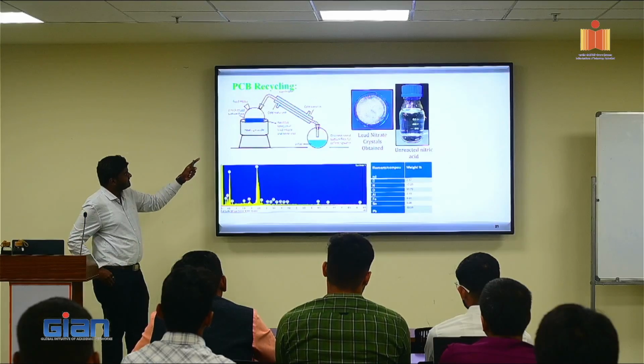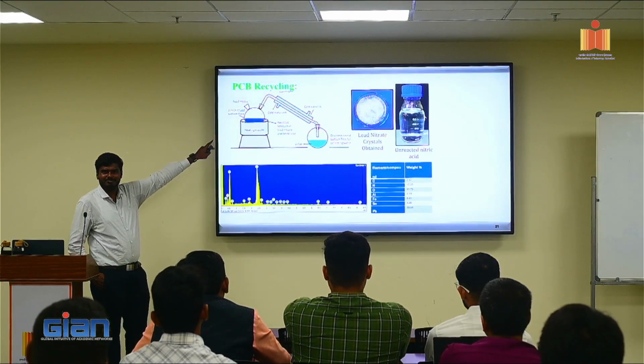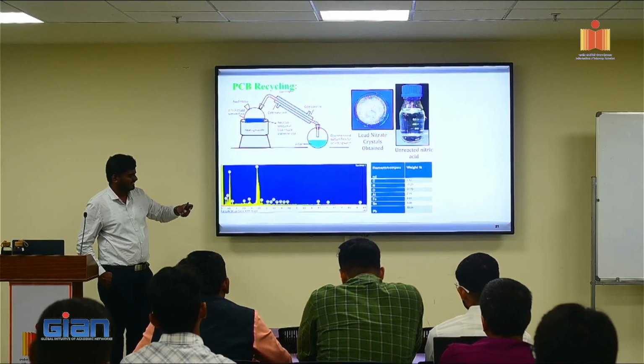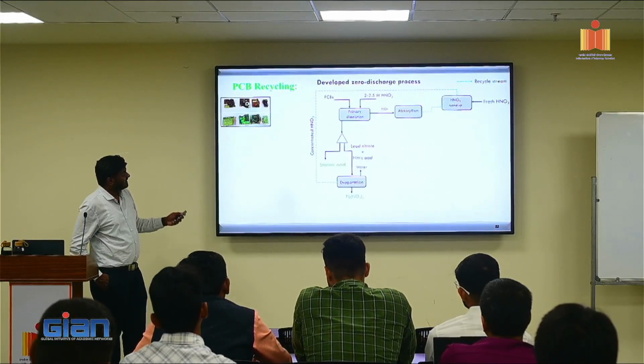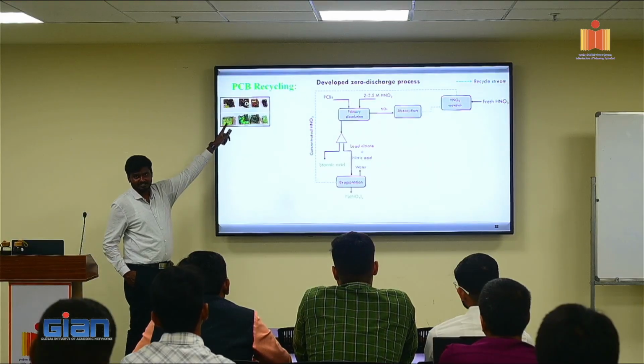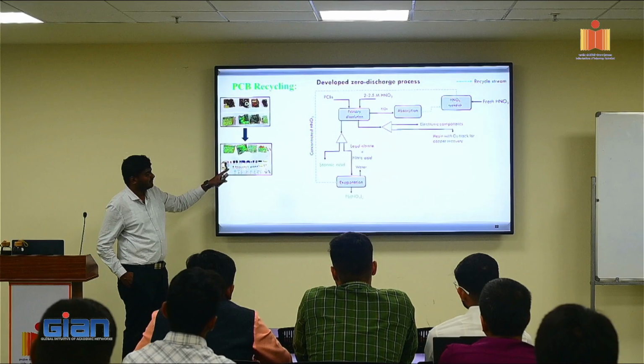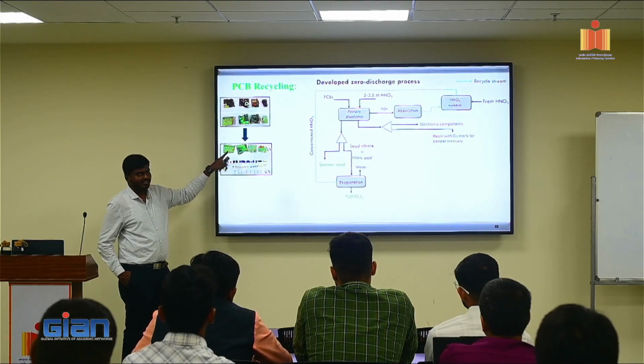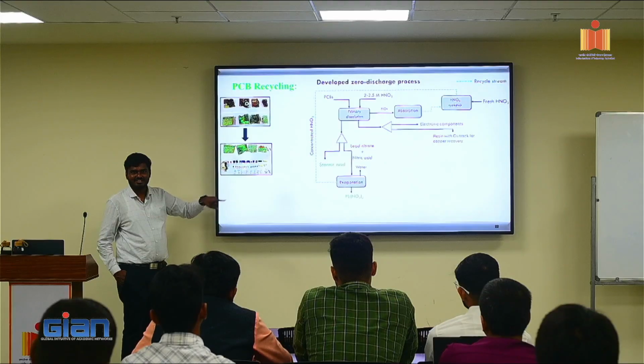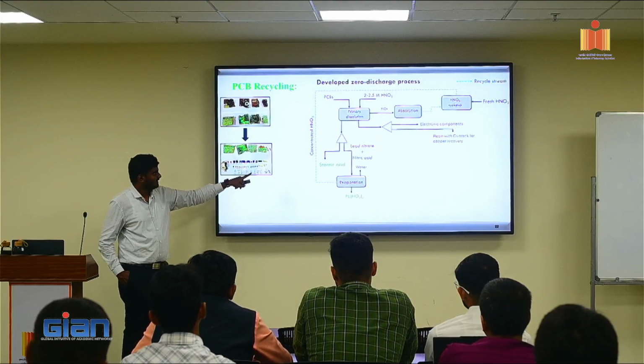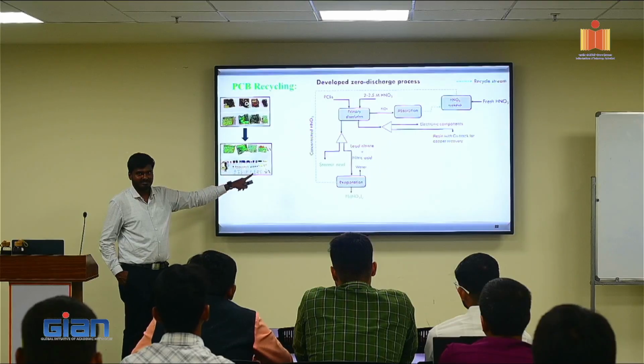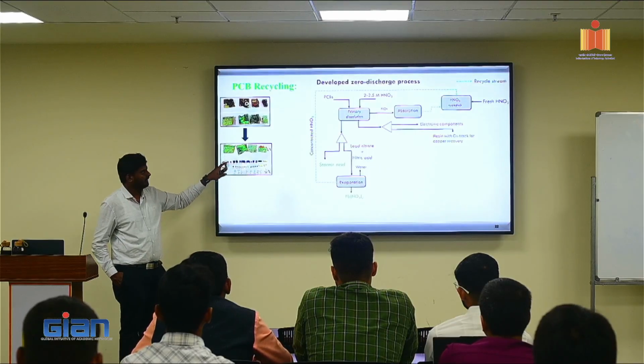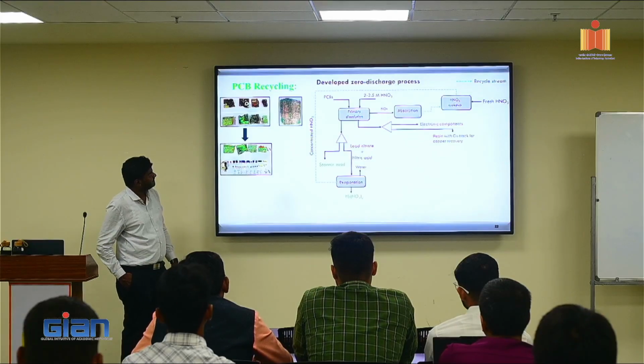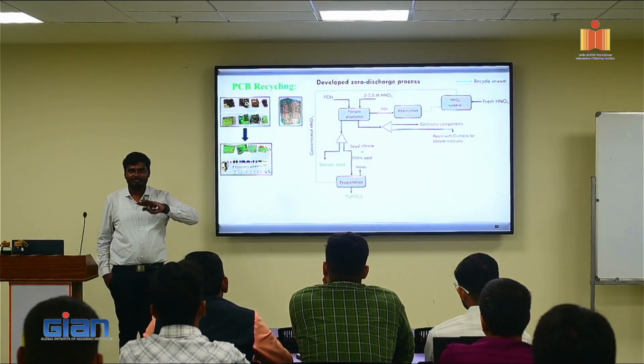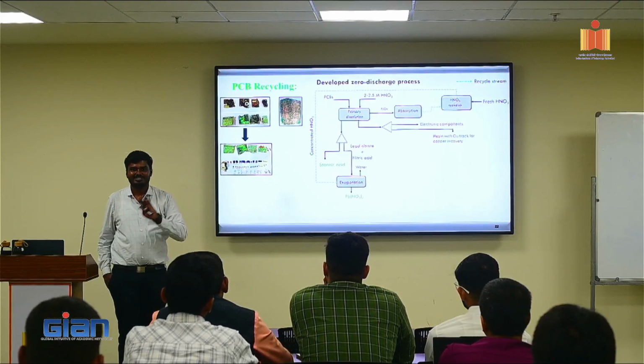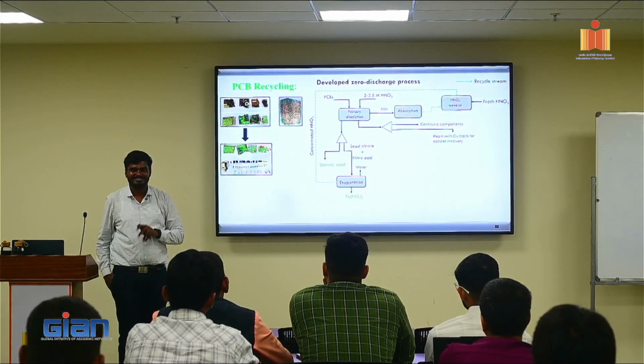So this was the separation, the simple distillation unit that we used to get these lead nitrate crystals. We analyzed it. Now we had these printed circuit boards. After primary dissolution, it looks something like this. All the soldering got dissolved. When you vigorously shake it, all the electronic components get separated out. You can see that I have lots of different types of electronic components on the boards. And if I focus on one board, you can see the copper below that epoxy layer. But I don't want to scratch it, I just want to recover the copper as it is.